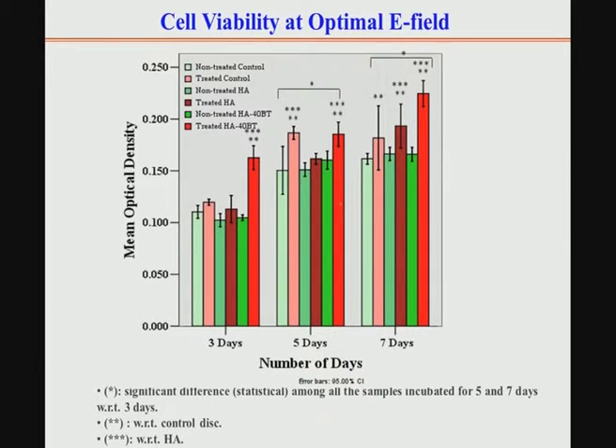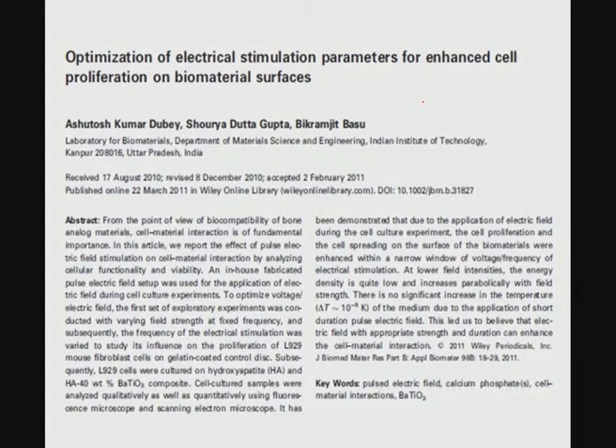Okay. Now, one of the things that is a valid question in the cell biology field is, when you give this electrical stimulation and grow these cells for different time points in culture, like 3 days, 5 days and 7 days, whether after that the cells' growth pattern changes because they are given certain biophysical stimulation. To address this, we have grown these cells after they receive the electrical stimulation for different time points in culture, and we have seen that they show a standard linear increase in the MTT optical density values, essentially showing that mitochondrially active cells, or cell viability, increases with increasing time point in culture. So, there is no alteration in their growth pattern because of this electrical field stimulation. This work is published in JBMR B in 2011.